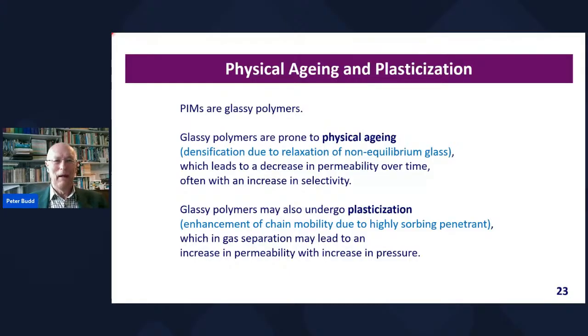And so by one process or another, over time, glasses do tend to very slowly relax into a slightly more dense state. And in terms of permeation behavior, that leads to a decrease in permeability, often with an increase in selectivity, but it's a change. And chemical engineers don't like materials that change over time. So that's something that we probably can't get rid of entirely, because the glassy polymers aren't equilibrium. But it is something we can try to control, and I'll talk a bit about that.